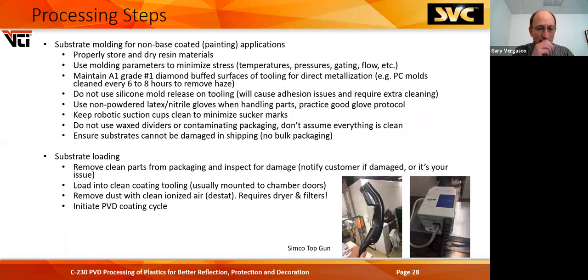So when you're molding substrates specifically for non-painting applications, you need to properly store and dry your resin materials. You have to use molding parameters to minimize stress. It's the temperature of the process, the pressures, the gating, the flow. And this is not something molders like to do. In thin parts like cell phone covers, the edges can be very highly stressed. Sometimes you've got to slow the molding process down in order to get the stress out of the part.